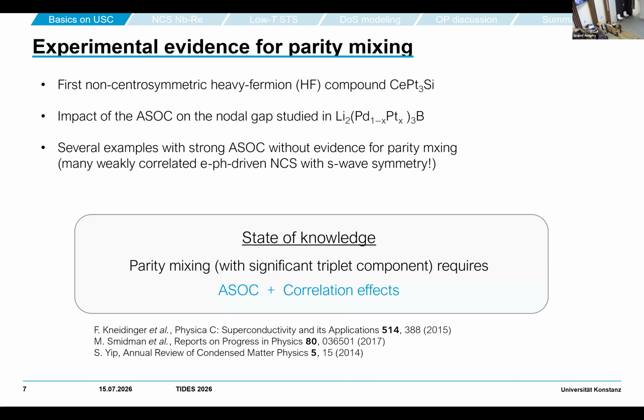There are also some indications for asymmetric spin-orbit coupling, which gives rise to this parity-broken order parameter. But in the literature there are also many examples where, despite having this strong spin-orbit coupling, there are no indications for triplet superconductivity—everything can be described with S-wave symmetry. So the open question is whether it is always necessary to have these strong electronic correlations, present in heavy fermions, together with spin-orbit coupling to have triplets, or whether it would also be possible to have triplet components and a parity-mixed order parameter with spin-orbit coupling alone.